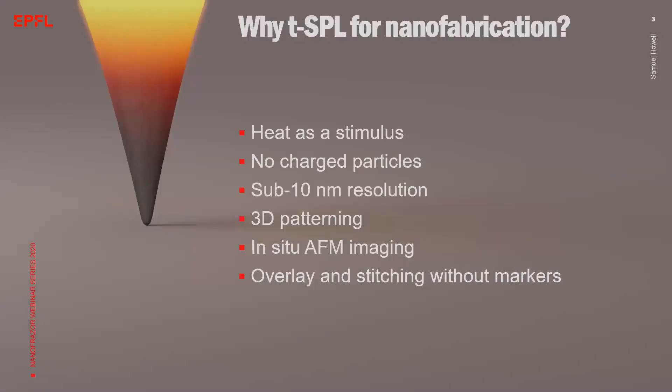Let us dive right into the reasons why TSPL is an excellent technique for direct-write nanofabrication. First, it uses a stimulus heat instead of charged particles, which means that structuring of low-dimensional materials and devices is possible without inducing defects such as trapped charges. The technique reaches a lateral resolution of less than 10 nanometers in a single fabrication step, and 3D patterning is straightforward and directly related to the indentation depth of the tip. A major advantage of TSPL is that the cold tip can be used as an AFM to image the surface topography. Therefore, overlay of patterns on structured substrates or stitching is possible without the need for alignment markers. Even monolayers of 2D materials can be detected under a thick layer of resist.